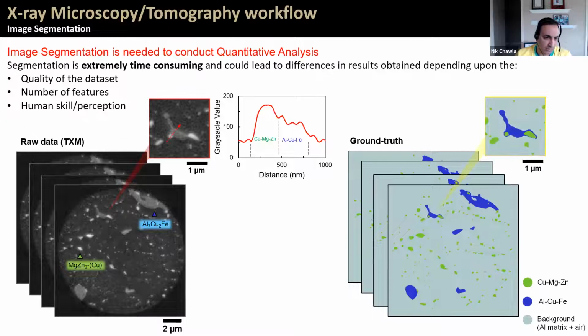So here, for example, we have MgZn2 particles. We have Al7Cu2Fe particles. We know this through EDS, what the composition is. And the background here is the aluminum matrix. So we have essentially three, actually this MgZn2 has a little bit of copper in it. So we want to be able to separate these three main phases: the aluminum matrix, the MgZn2, and the Al7Cu2Fe. These are the three main phases.